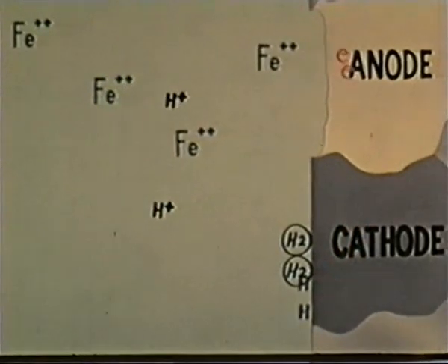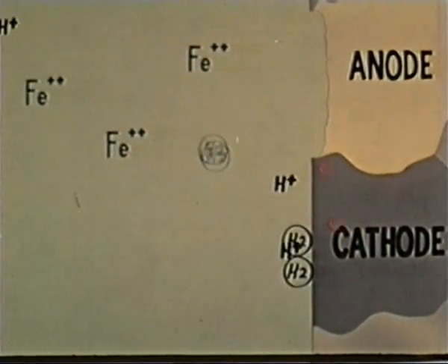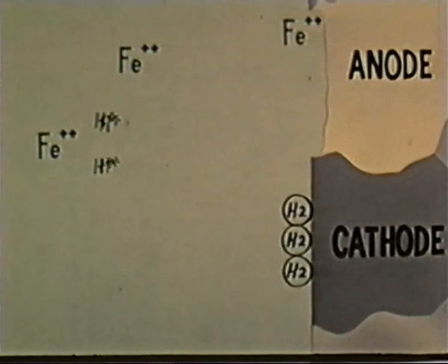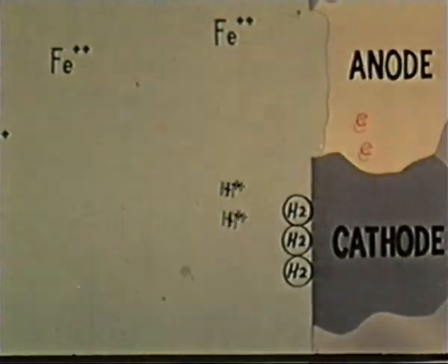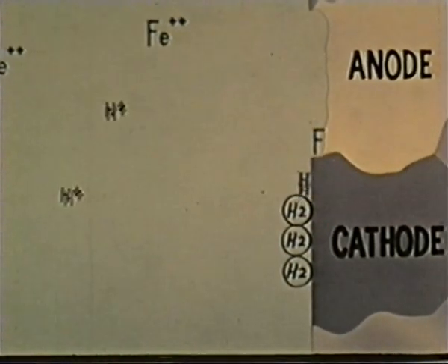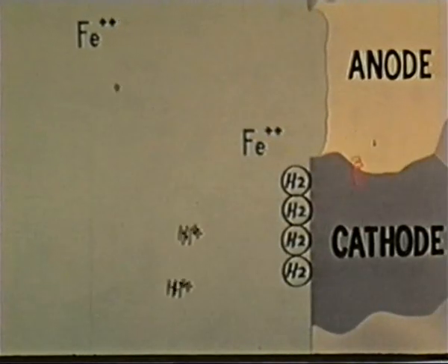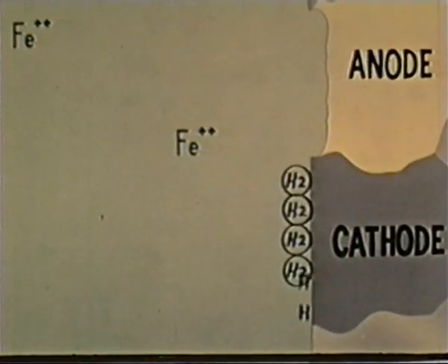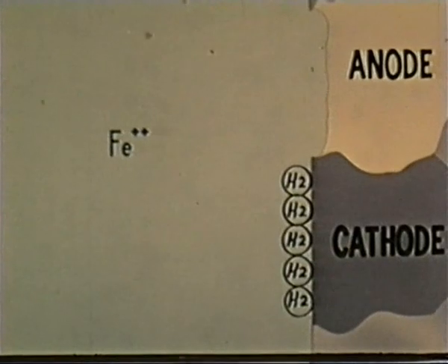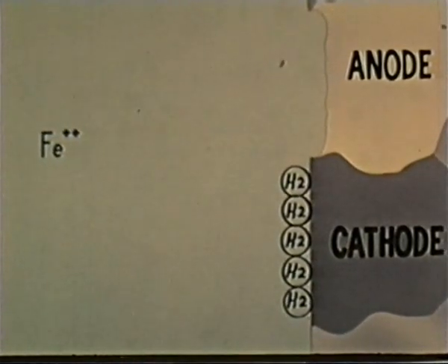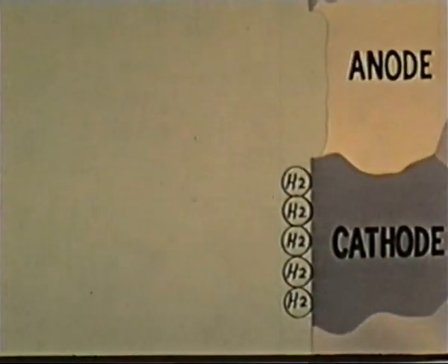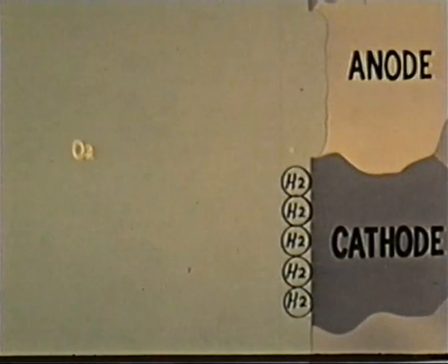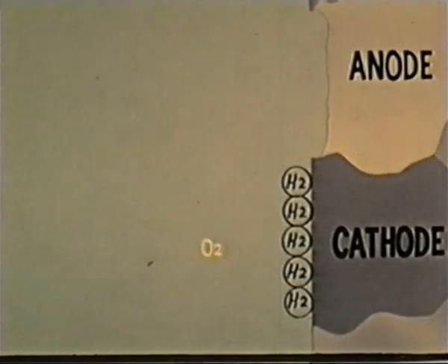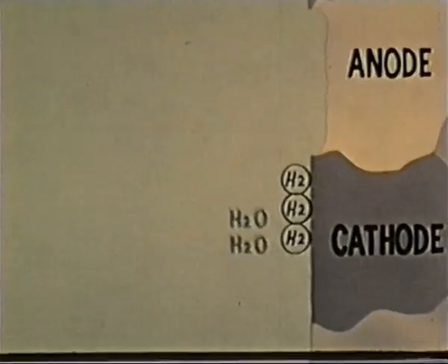Reactions involving oxygen dissolved in the electrolyte can also occur to complete the cathodic reaction. Oxygen can react with the accumulated hydrogen to form water, and by removing it, may permit corrosion to proceed. In doing this, oxygen acts as a cathodic depolarizer. As such, in neutral solutions where the hydrogen ion content is quite low, the concentration of dissolved oxygen and/or its availability are usually the rate-controlling factors in the corrosion reaction.